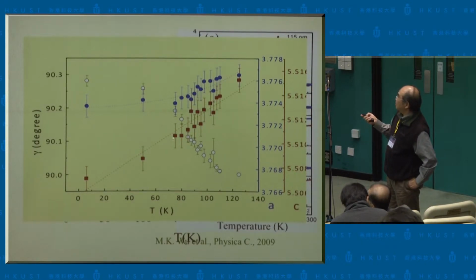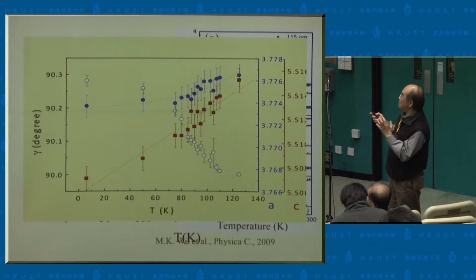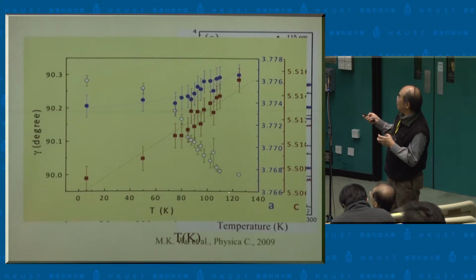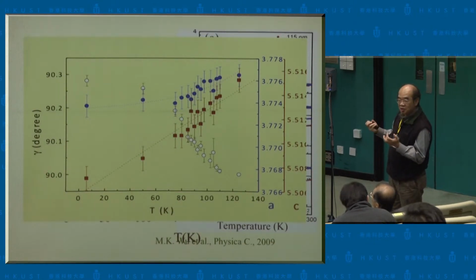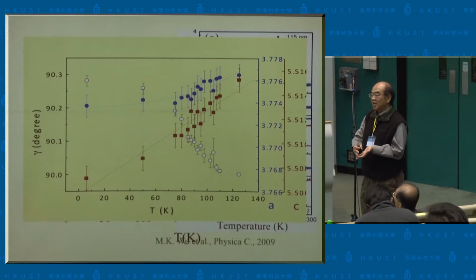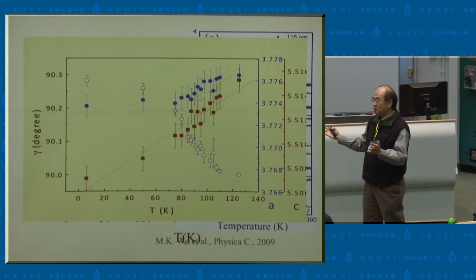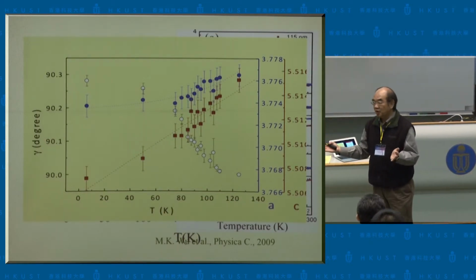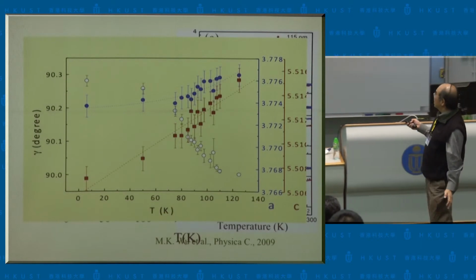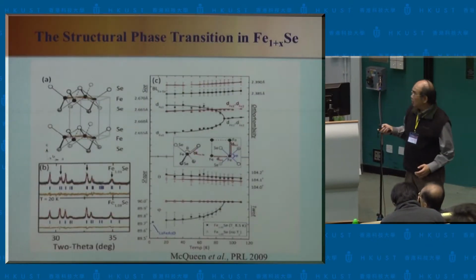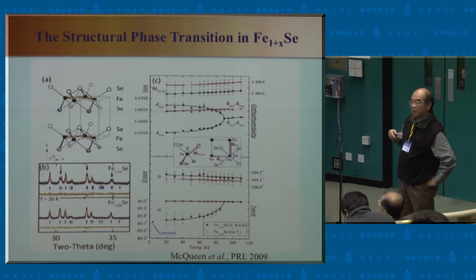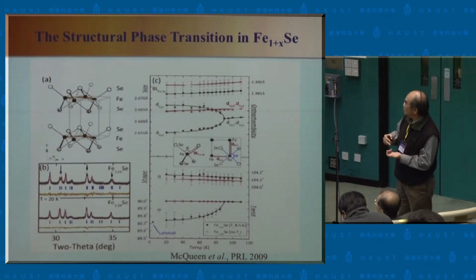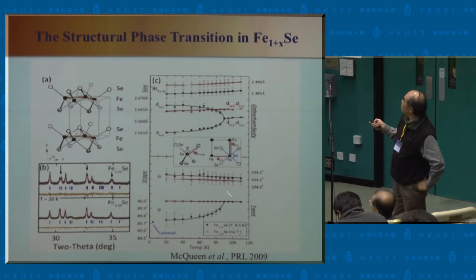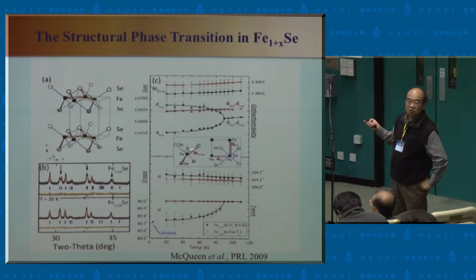And this is the structure information we have in the iron selenide that shows the superconducting transition. You see that there's a small distortion. Actually, it's really not that big. It's just the gamma angle that tilts from 90 degrees to 90.3. So essentially, below 90K, you convert this from tetragonal to some kind of orthorhombic phase. But interestingly, this is the work by Cava's group, but we also have another using chemical doping, using thin films, a different kind of technique. It clearly demonstrates that this low temperature distortion is essential for superconductivity.